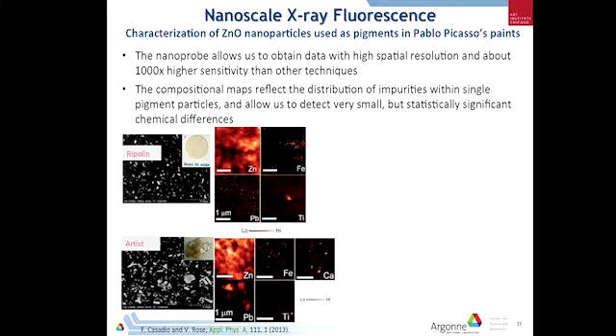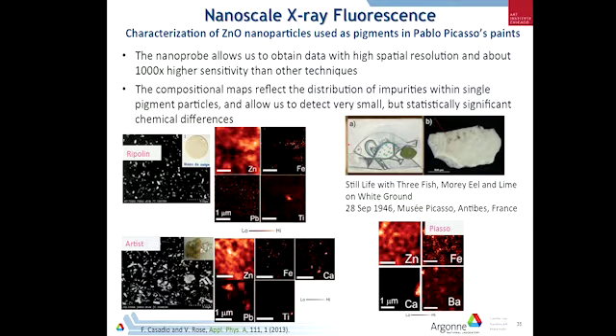But if you look at how the iron is distributed, or how the titanium is distributed, or how the lead is distributed, the kind of scale, the size of the features and how far apart they are is different between the two. And so by looking at that and by then comparing with this little tiny flake of paint that came from somewhere over here on this painting, we were able to compare the distribution of the elements in that paint with these two types of paint. And what it turns out is that, in fact, house paints were used to paint both the painting in the previous slide and also this painting here, the red armchair. And that's Volker Rose from CNM and Francesca Casadio from the Art Institute.